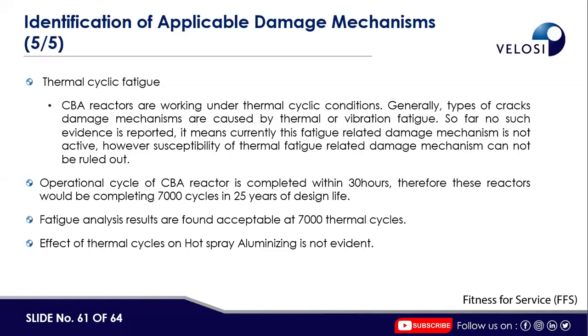The operational cycle of the CBA reactor is completed within 30 hours. Therefore, these reactors would be completing 7,000 cycles in 25 years of design life. Fatigue analysis results are found acceptable at 7,000 thermal cycles. The effect of thermal cycles on hot spray aluminizing is not evident as such.